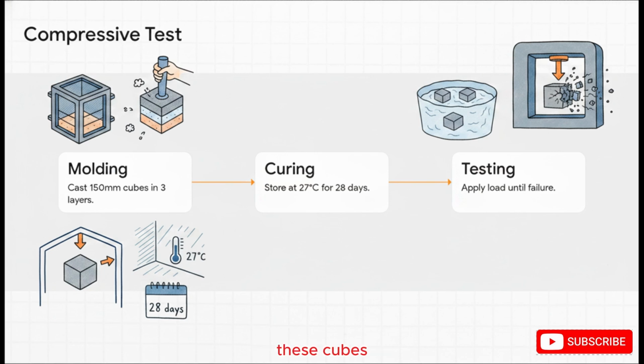Then comes the waiting game. We cure these cubes in a 90% humidity room at 27 degrees Celsius, usually for a full 28 days. Once they're fully cured, we place the cube into a massive compression testing machine, a CTM, and we don't just abruptly smash it. We apply continuous, steady load at a rate of 140 kilograms per square centimeter every single minute until the concrete finally gives up and shatters.